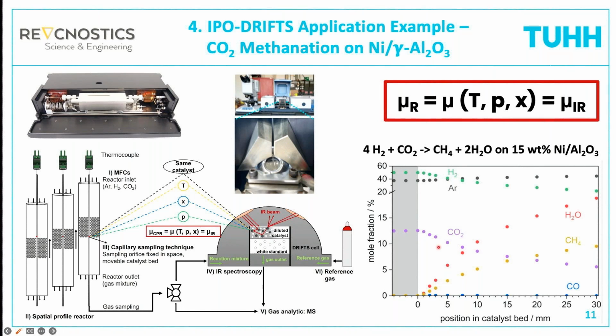And here on the right side, you see first the stoichiometric equation. So 4 H2 plus CO2 gives CH4 and 2 H2O. So we have a contraction of moles from 5 mole to 3 mole. And you can see now the profiles that we get from the compact profile reactor. 0 in all of these plots marks the inlet of the catalyst bed. And you see before the catalyst bed begins, we have no conversion. So we have a horizontal line.